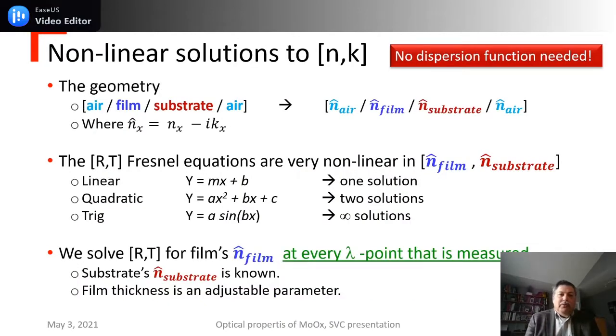Now, what we will do is take the geometry of one film on one substrate where we know the refractive index of the substrate, and we can express it as the complex refractive index n minus ik, which is the normal way to express the refractive index. And we should realize that the reflection and the transmission, which we can write down from various Fresnel equations, are extremely nonlinear in the refractive index of film and substrate.